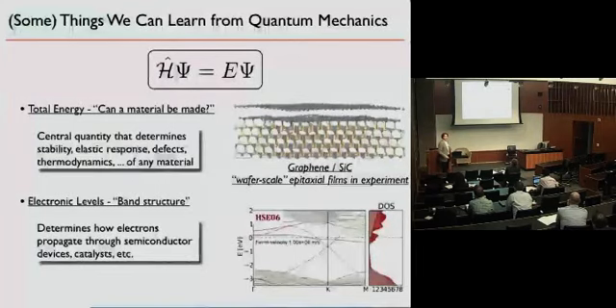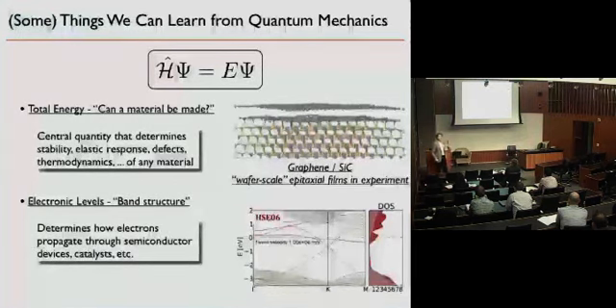But interestingly, people have also focused on the other side of this crystal. What's subtly not apparent perhaps too much unless you know it, is that this crystal has two sides. One side where the silicon atoms are on top, and one side where the carbon atoms are on top of these bilayers that form the crystal. If you try the same thing on the carbon face, and people have tried this for a long time, you don't get such nice films, although you get higher mobilities in the films that you do get. But it turns out that the single layer graphene films are actually not thermodynamically stable on that face because other phases get in their way.